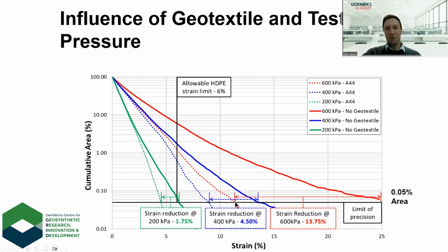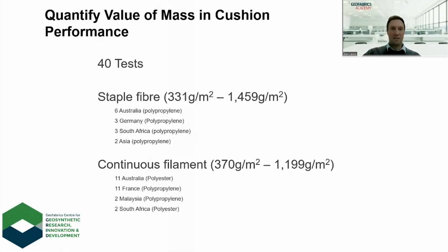And you compare that to an A44 cushion protecting that HDPE under the same load with the same rock, it brings it back to about 12%. So it's a huge reduction in strain, although it's still above that limit. So what that does tell us is that we'd have to increase the geotextile grade to something that's a bit heavier. And then we took it one step further because we're trying to understand what impact the type of geotextile had, aside from just its mass and technical data.